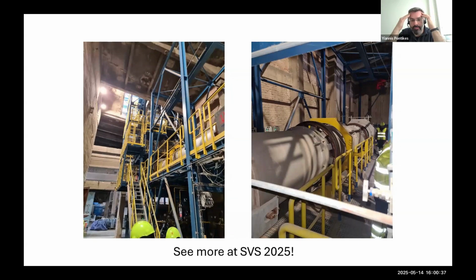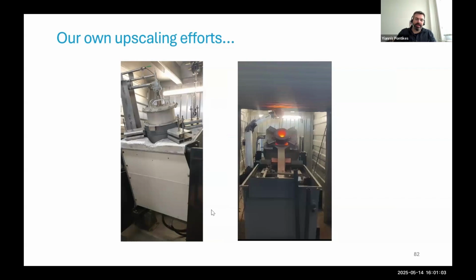So we did make, with people of Holcim and people of Czech Republic, this glass in a very, very big furnace, and we have received the material, and it's fine. You need to change the refractories, but more details you can find in the slag valorization symposium, where there was a presentation, and you can see more in the proceedings. So there is also hope for the industrial upscaling. This is what we've done in the lab. I think it's interesting because we converted an induction furnace into a rotary induction furnace.